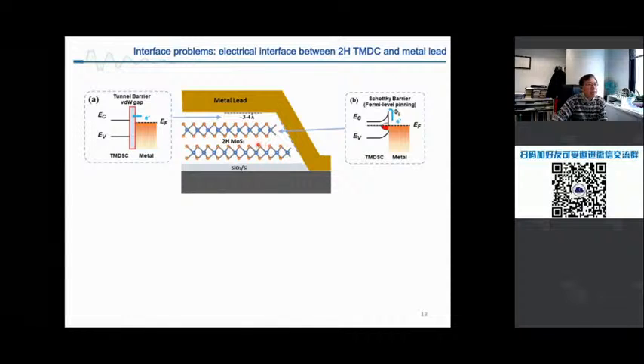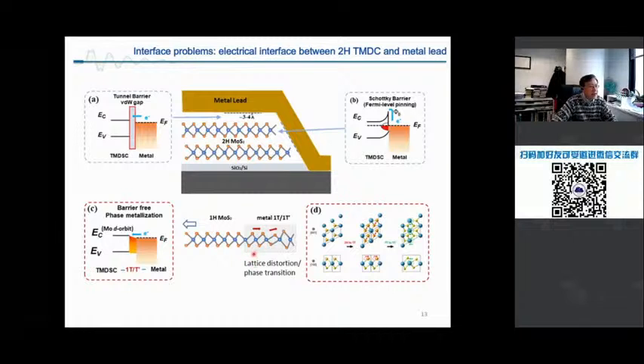So if you look at the mechanisms, I show you a cartoon to show the interface structures. On the right side, with the dangling bond, there's a high Schottky barrier. If I simply deposit metal on the top surface, because there's no bonding, there's no charge effect, yes, but there's a van der Waals gap. You have to inject current through the tunneling effect into the materials, and the efficiency is not high. Right? So the ideal solution is that if you can convert part of the 2H semiconductor phase into a 1T or 1T prime, anyway, it's named here as distortion phase transitions, and that phase is metallic, and then use metals to make contact on this metallic phase and make ideal junctions.